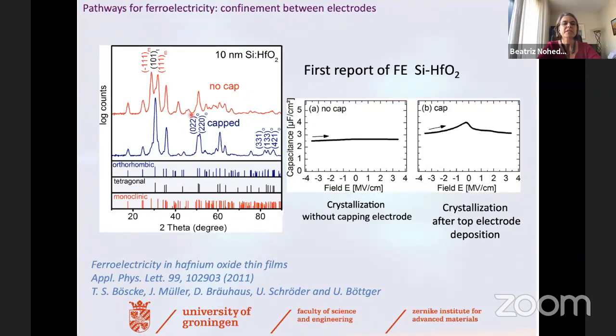So if the material was not confined between electrodes and it was not crystalline, this peak was not there. Looking more closely at these films, you have to realize these films were very, very thin, because these are the typical thicknesses one uses in microelectronics. Also, any structural characterization is enormously challenging. So you cannot really look at the atomic structure in detail. You can look maybe at the total symmetry. You can compare one phase with the other, but you cannot really say a lot about the exact atomic positions.